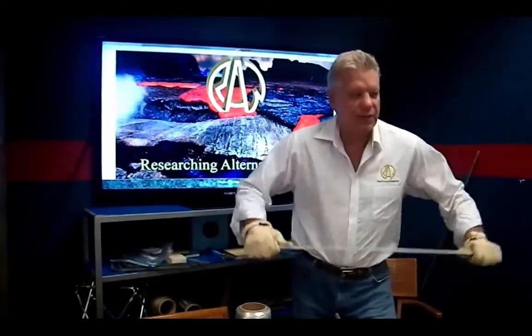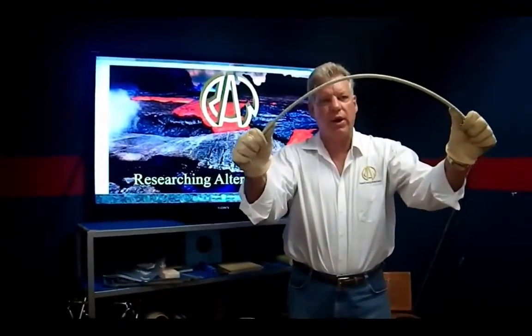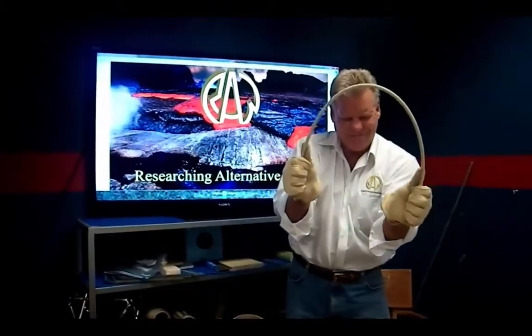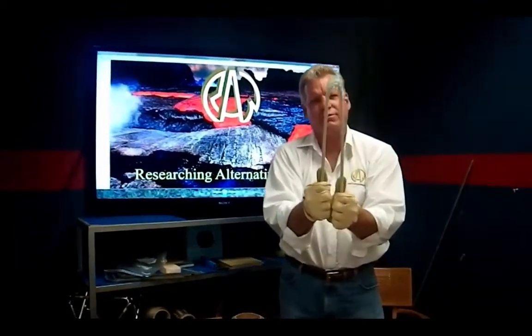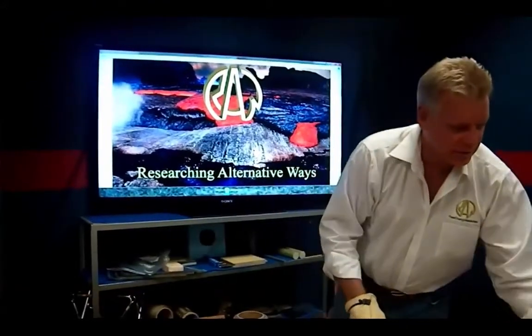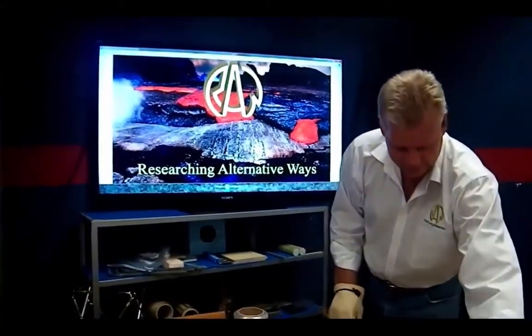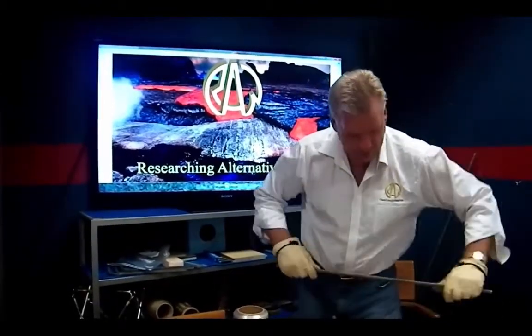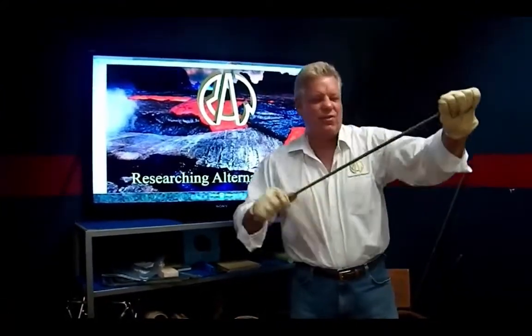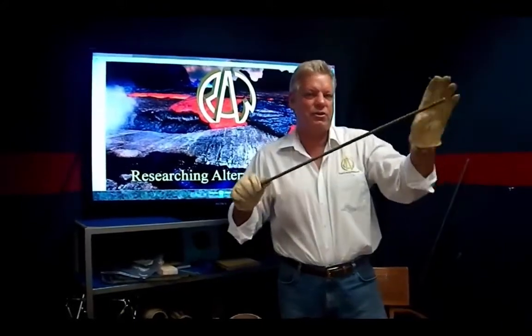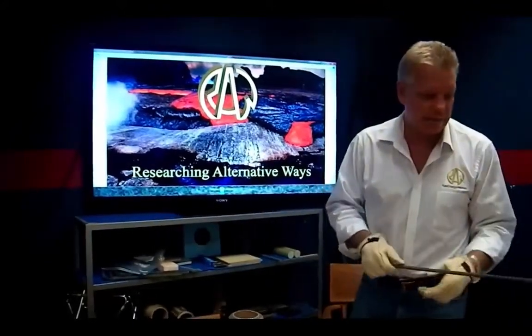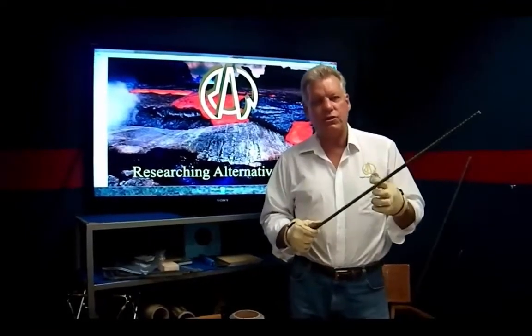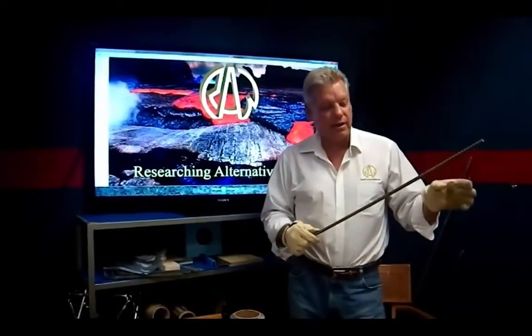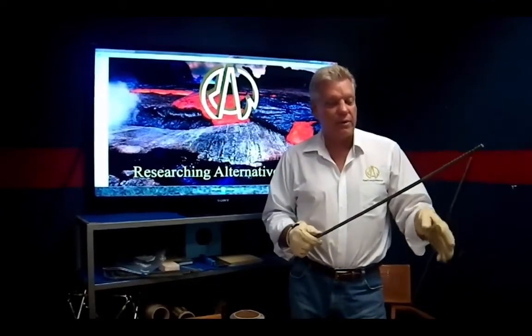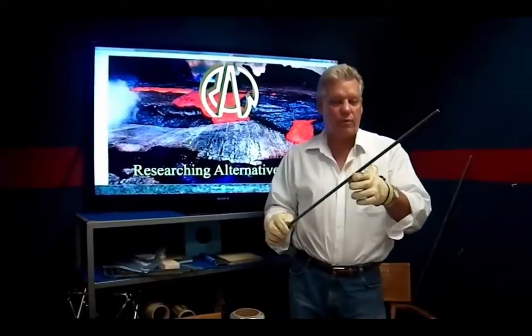You watch, I bent the steel, and this bends quicker, and if I push on it hard enough, it will rupture. Basalt is a bit more tenacious than that. That's about the same length as that one. You can clearly see that it doesn't even want to begin to bend early on as much as the fiberglass did. That's because its modulus is 100. Again, steel was 200, fiberglass 50, basalt 100.